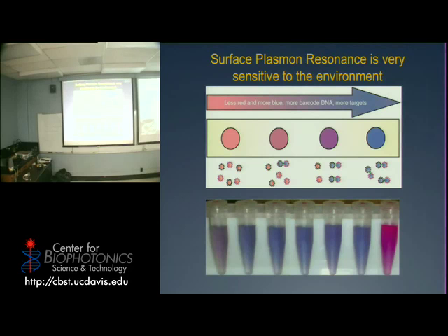So the 5 nanometer particle has a much more intense electrostatic field because you have a charge that gets confined into a smaller and smaller volume. I think the analogy is really not appropriate, but think in terms of a black hole, right? Where you have all this mass centered in a very small volume. So with the 20 nanometers, it takes just a drop of an electrolyte to shield these electrostatic interactions. With the 5 nanometers, because of the size, and also it's a surface, so it scales to the power of 2, you have a much more intense electrostatic field. You need much more than 100 millimolar sodium chloride to shield that effect.